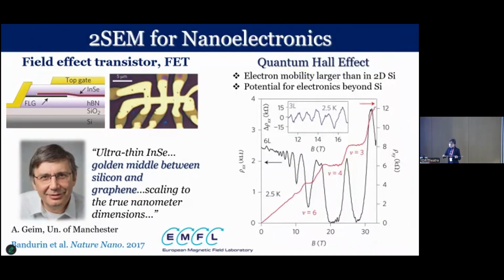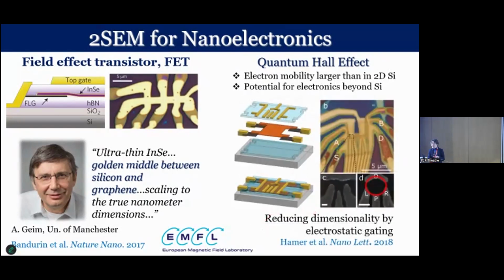And an important indication of the quantum nature of the electron transport is the quantum Hall effect, the quantization in the electrical conductivity that we could clearly see in this multi-layer structure where the electrical channel is the 2D semiconductor inside. And of course, once you have a nice two-dimensional electron gas, you can further confine the electron motion to create, for example, a quantum dot or a quantum wire to additionally confine the transport.